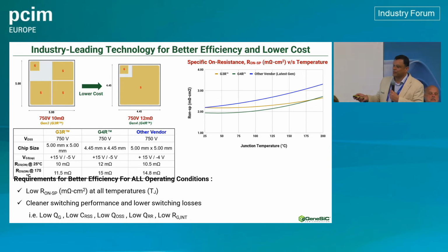So, for example, for automotive traction applications, we have a present device, which is a 5 millimeter by 5 millimeter, moving to a Gen 4, which would be a 4.45 millimeter by 4.45 millimeter, which has finally at high temperatures, the G4 technology will offer 15 milliohm as compared to a competitor's 14.8 milliohms, while still having very low RDS on at room temperature. Why is this important, even though this seems like a higher tempco?